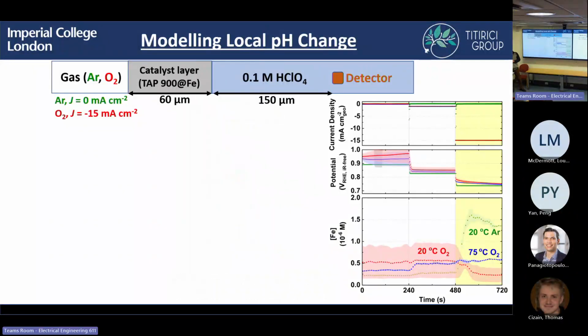And so this was developed by a colleague in France, Antoine Bonnefond, where they developed just a very simple microkinetic model where you have your catalyst layer. And we measured this, which is 60 microns thick. And then we have our ICP-MS detector, which was only 150 microns away from the catalyst layer. And then because we're using a gas diffusion electrode setup, on the back side, we have our argon or oxygen. So this is essentially how we display the model.